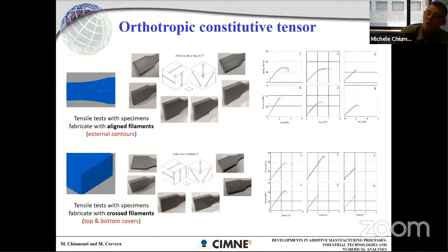At the end of the day, we generate specimens with aligned filament, as the one on the top, and the cross filament, 100% infill, 45 minus 45, and using different printing orientations, we were able to characterize the constitutive tensor. Observe that typically what you obtain at the end of this work is a fully orthotropic tensor of the material. You can simplify a bit without loss of accuracy as a transversal isotropic material, but still not isotropic.